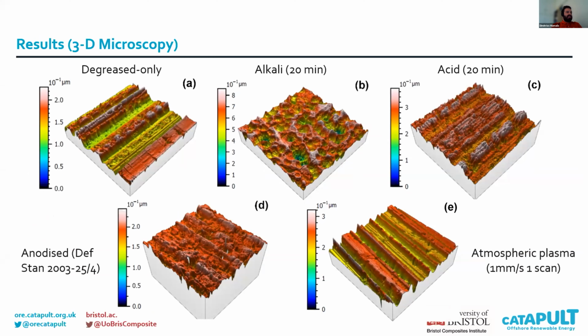In this slide, you can see images taken with a 3D microscope of the aluminum treated plates after the application of the different surface treatments, using a coherent scanning interferometer. It is clear that the applied methods resulted in different topographical characteristics, as well as varying surface chemical functionality. In turn, different mechanical and chemical interlocking phenomena are expected between the thermoplastic resin and the metal phase, affecting the bonding strength of the hybrid system.